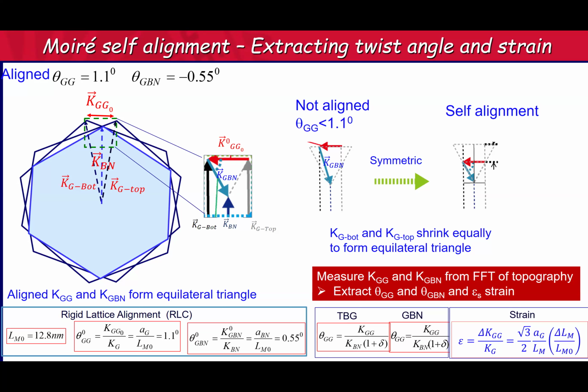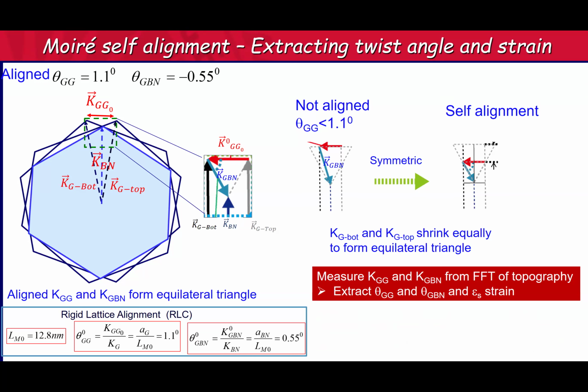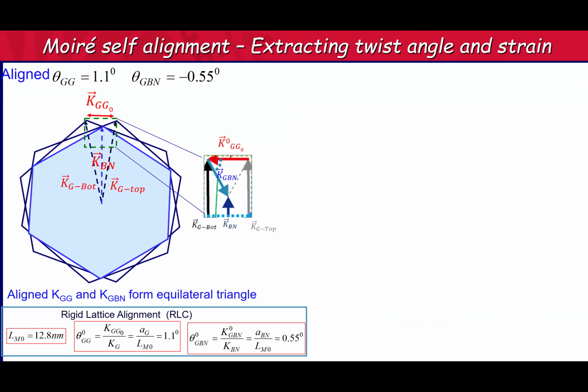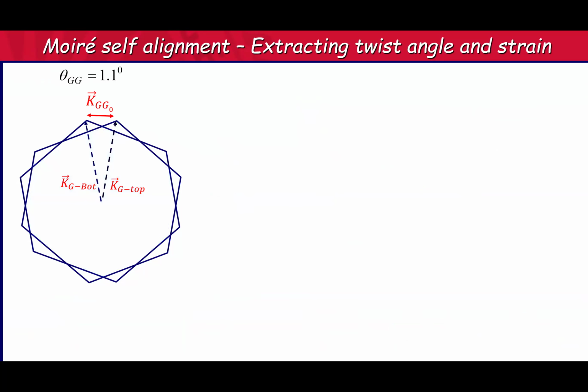And then in order to align it with the GBN, there's 3 angles: plus 0.55, minus 0.55, and 0. But the 0 one is a higher order thing, so it's going to be much weaker. Why are plus or minus 55 so rare? What is the main constraint? Is it that you just need to stay within the angle range that gives you still good flat bands? No, because you showed the example where the unit cell is just three times more. You need 1.1 degrees to have the flat band. That is fixed, you can't vary that much, that's rigid, because we want the flat band.